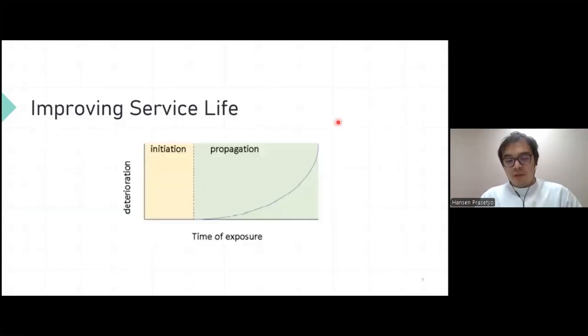And how to improve it? We must first see how deterioration happens in concrete. I think this was covered by Jessie already, but there's an initiation period and there's a propagation period. During the initiation period, deterioration doesn't really happen. It's just a buildup of chlorides in the concrete cover. And then when it reaches a certain threshold, it turns to a propagation period where corrosion happens exponentially, and the reinforcement starts to give up. So the idea is to prolong this initiation period to be as long as possible. That way, the propagation period will be delayed, and the service life of concrete can be extended.